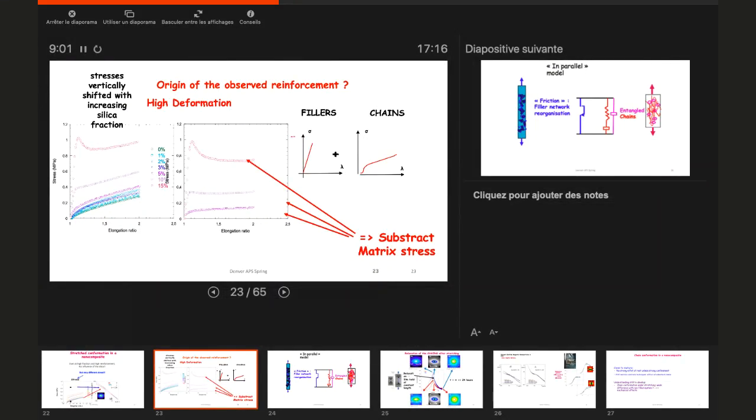And this would be very interesting on attractive nanocomposites above the glass transition. For example, if you take this P2VP above the glass transition and you do this kind of test, because now the polymer and the silica like each other, then we may see the stretch of the chain during elongation.